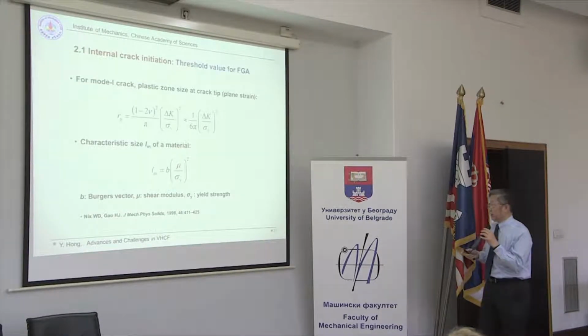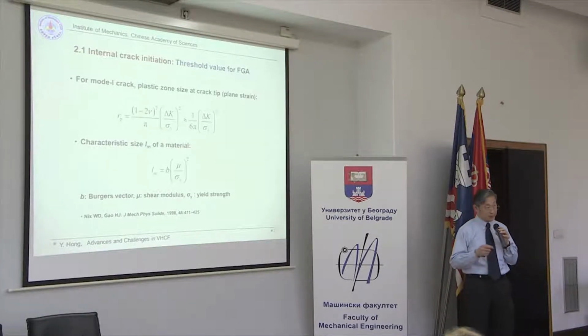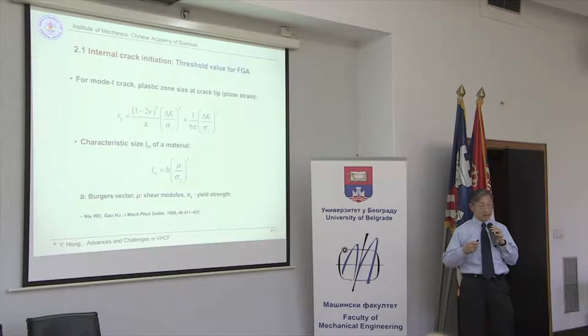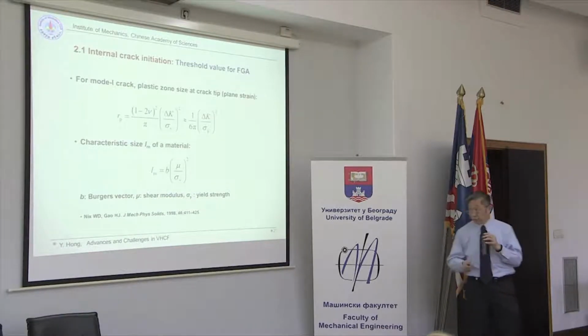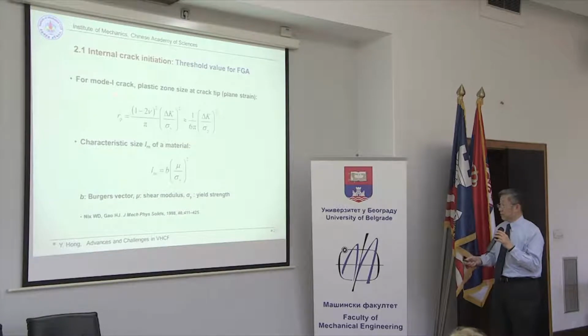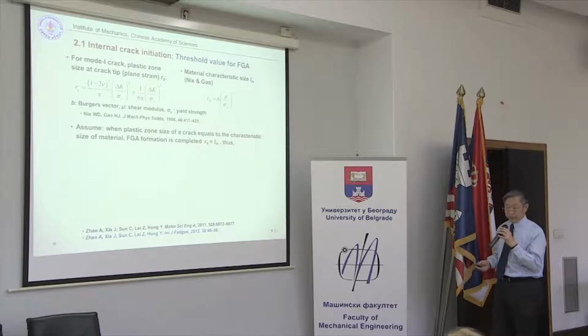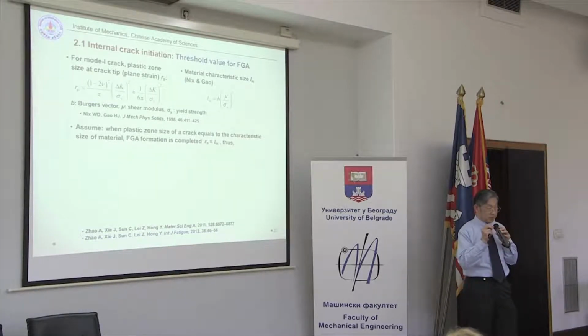So we try to estimate, how can we calculate the value of delta K for this crack initiation region. And we use these expressions. The first is the plastic zone size at the crack tip, and the other is the size of the characteristic microstructure of the material. And the important point is that we assume when the plastic zone size at the crack tip equals the characteristic size of the material, the development of this initiation region will be completed.